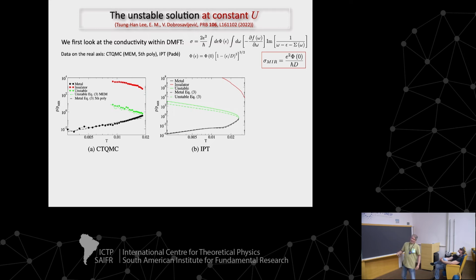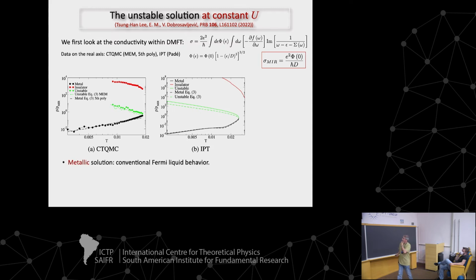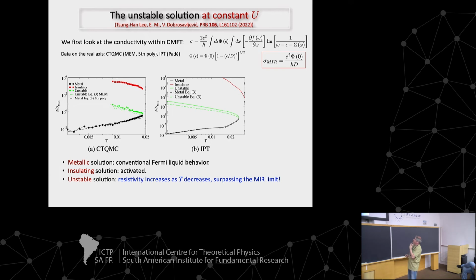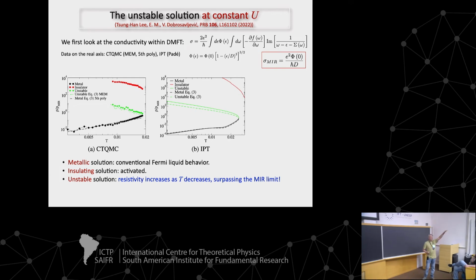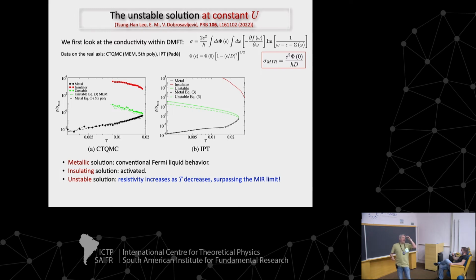Usually, for instance, in this QMC, quantum Monte Carlo method, you generate data on the imaginary axis. You have to do some sort of analytic continuation to the real axis. So these are different methods of doing that, which is why there are two curves in these plots here. This is for perturbation theory. This is for quantum Monte Carlo. They are different approximations, of course, but they have roughly the same kind of behavior for the metal, for the insulator, and for the unstable solution. So the unstable solution has a resistivity that increases as T decreases, but it's not really like an insulator.